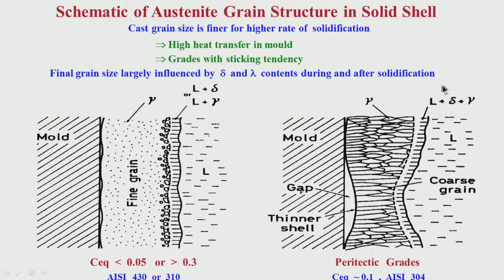Initially liquid goes to delta, and then it goes to liquid plus delta, and then delta to gamma. That means gamma transformation is taking place towards the end of the solidification. So, this creates a depression tendency. Depression means there will be an air gap between the mold and the solid shell. So, the solid shell will become thin because it is a hot spot formation.